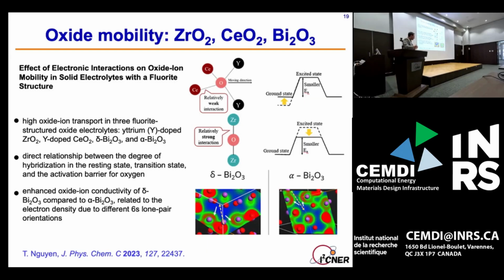So what we looked at is that bismuth is not really the typical metal oxide as everything else. Bismuth is actually a post-transition metal element, much more similar to phosphorus and to nitrogen. It has a lone pair, and this lone pair, unlike the other transition metals, has strongly localized electrons. Now, the crystal lattice can organize these lone pairs in such a way that they will open pathways for oxygen transition, or they will face each other and block the pathways for the oxygen transition. So here it was very important to understand that the different crystal structures will allow or forbid oxygen diffusion in the material by strongly localized electrons of the lone pairs.